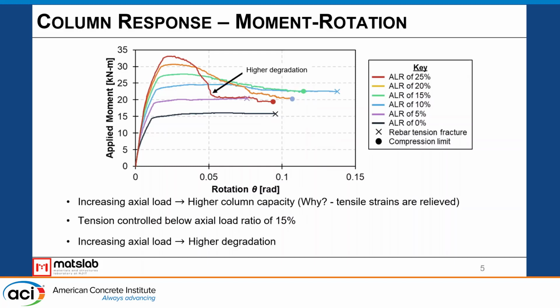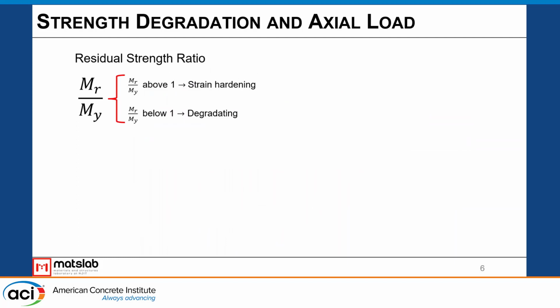And then lastly, what we can observe is, as we increase that axial load, we're seeing higher degradation and a loss of load carrying capacity. So to further understand how much capacity we are losing and how much we have left at that ultimate failure state, we defined what's called the residual strength ratio, and we took the moment at column failure divided by the yield moment of that particular column.